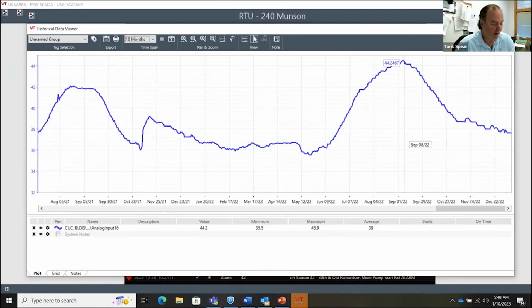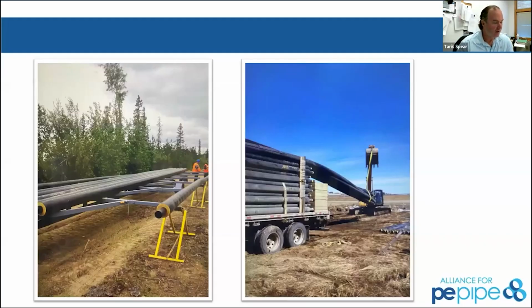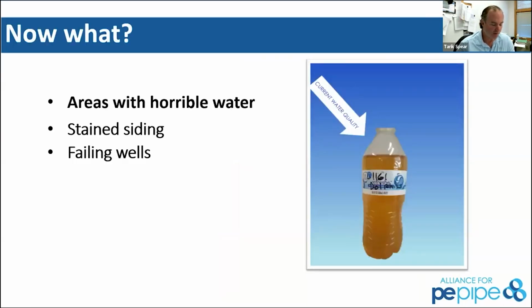Corrosion: 4 out of 5 of the leaks we have in our system are corrosion holes, typically in a pipe called 10 gauge. We have a lot of that. The other 1 out of 5 is typically in copper service lines.